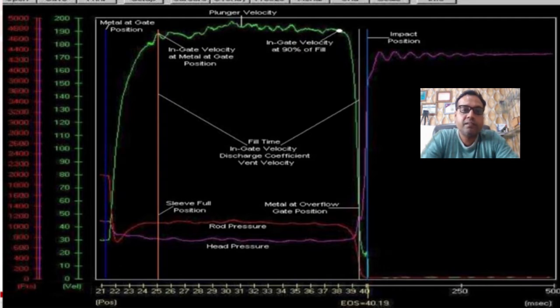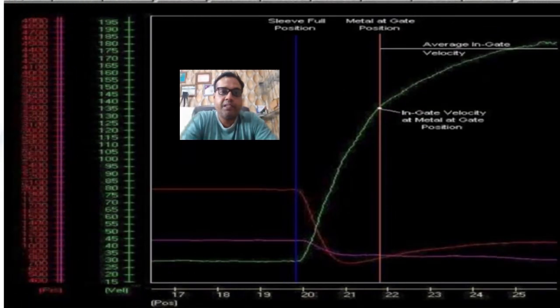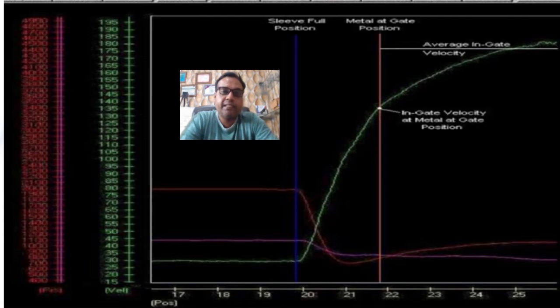Another process parameter during cavity fill is average in-gate velocity. This is the average metal velocity through the in-gate during the fill time. In the process monitoring system, it should be calculated by first determining Q, the volume flow rate of metal, and the gate area. The in-gate velocity is then equal to Q divided by the gate area.